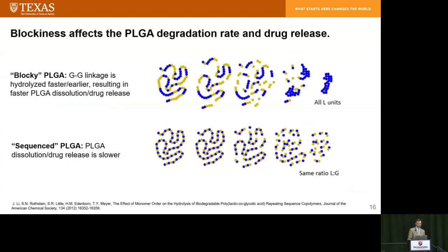And this matters because it affects the PLGA degradation process. The glycolide linkages, GG linkages, are hydrolyzed faster. So if you have a highly blocky PLGA with lots of GG, then those will be hydrolyzed faster, the PLGA will dissolve faster, and the drug release will be faster.